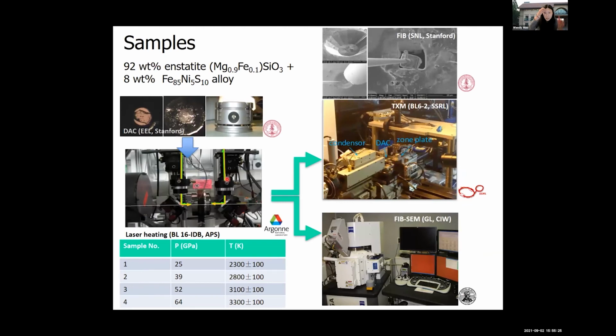I'm going to show some imaging on iron-rich melts and silicates that we quenched from a diamond anvil cell. This is work that was led by a former graduate student, Crystal Shi. The starting material was a mixture of enstatite and an iron-nickel-sulfur alloy. Crystal compressed the samples in a diamond cell, reached high temperature using laser heating, and I'll show results from 4 samples. We also collected high pressure-temperature diffraction at APS to confirm that the iron alloy was indeed molten and that we were recrystallizing the silicate in the high pressure bridgmanite phase.